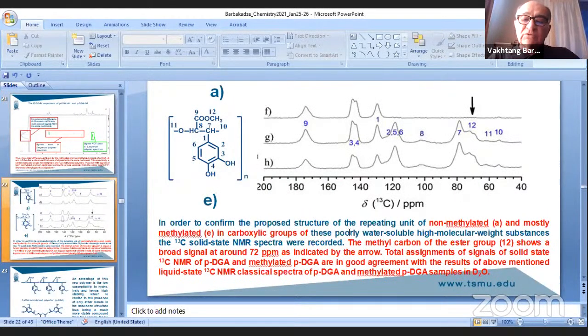In order to confirm the proposed structure of the repeating unit of non-methylated and mostly methylated carboxylic groups of these poorly water-soluble high molecular weight substances, the C13 solid state NMR spectra were recorded. The methyl carbon of the ester group shows a broad signal at around 72 ppm, as indicated by the arrow. Total assignment of the signals of solid state C13 NMR of the biopolymer and the methylated biopolymer are in good agreement with the results of the above mentioned liquid state C13 NMR classical spectra of biopolymer and methylated biopolymer samples in heavy water.